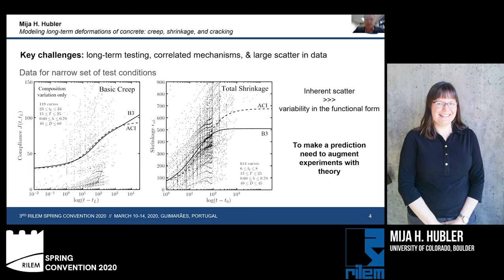The last point is a large scatter in the data. So here I have selected for a narrow range of concrete compositions, some data from a data set for basic creep, so that's an environmental isolation. If we look at the response to the loading, you see this large amount of scatter of the compliance of the material as a function of logarithmic time. And I've superimposed two existing models that are making an attempt to make sense of this type of data. The same is seen for the total shrinkage behavior. We have so much enhanced scatter in our data that the variability in our functional form is much less. So the only way we can work with this type of data is if we augment our experiments with theory that will allow us to subset our data and make better prediction models.